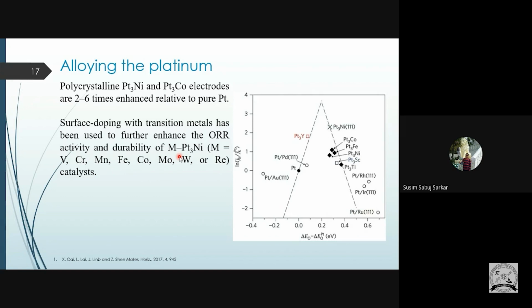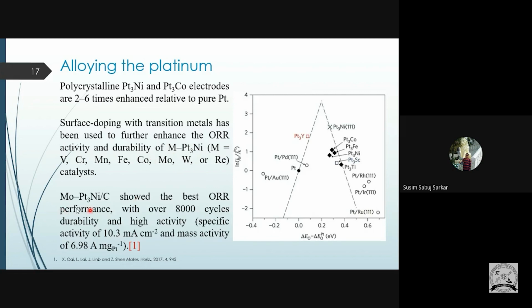So in that case, we have to place some non-precious metal which is durable. We know that iron and cobalt are durable, so we can combine them with Pt3Ni to increase the durability. Among them, molybdenum Pt3Ni over the carbon electrode shows the best performance over 8,000 cycles, with durability and high activity. So that is an approach, but we are still using platinum, and platinum is very costly.